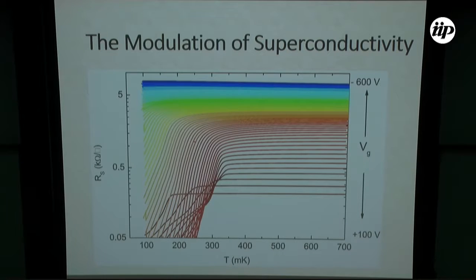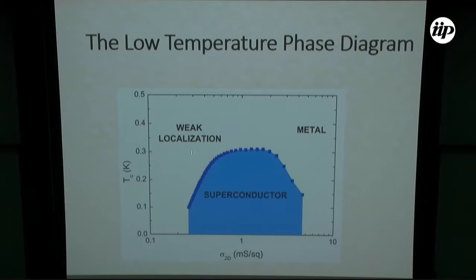So we can put TC as a function of the normal state sheet conductance in a phase diagram, and we see that we have this dome-shaped behavior of the superconducting state as a function of the 2D sheet conductance. So on one side we are bounded by the weakly localized state, on the other is a more metallic state.